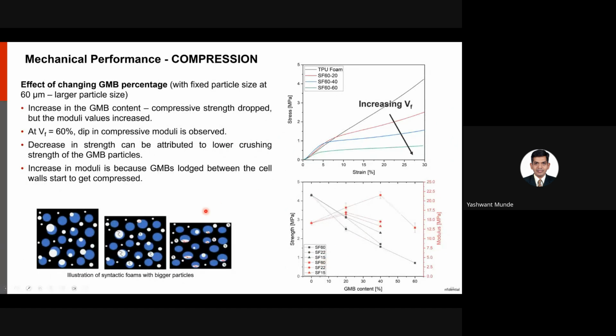So here we see that as we increase the volume fraction, we change one parameter at a time. We fix the particle size to the largest particle, 60, and we change the volume fraction from 20 to 40 to 60. We see that increasing the GMB content, the strength dropped. This can be attributed to the lower crushing strength of the GMB particles. As you may recall, the larger particles have the lowest crushing strength, and they also create bridges between the cell walls, causing their compression and collapse, resulting in this reduction of the plateau region.